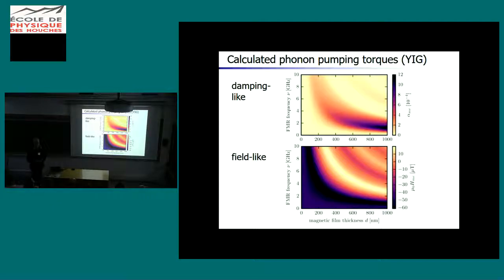I should mention that there are also torques due to this phonon pumping. They are damping-like and they are field-like. There's also a small field-like component, which is indicated here. It's not very large. It measures in microtesla. So this is a damping which we always have if we have a thin film of YIG on an insulating substrate, which becomes more important if you go to thinner films, and the increased broadening which people measure might be partly due to this effect.